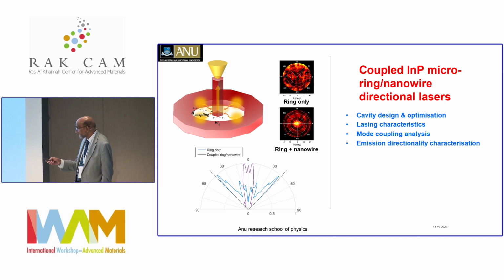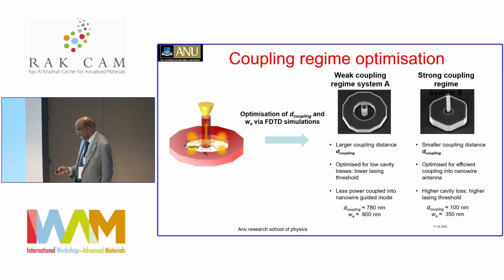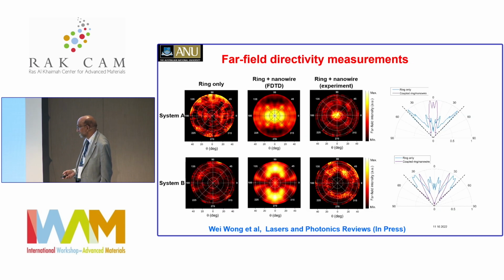What happens is that the light starts leaking out in the vertical direction. You expect to have vertically emitting nanowire lasers. Again, using our selective area epitaxy, we're able to make these nanowire and ring structures, with the nanowire being far away from the ring and the nanowire being very close to the ring. We call them weak coupling and strong coupling. That allowed us to make the light emit vertically. Here are the schematics of these.